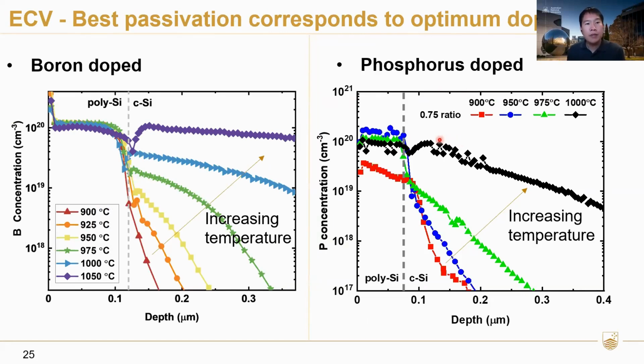Cool. So remembering that the optimum temperature is 950 degrees, these two images here show the ECV measurements of both boron doped and phosphorus doped. Essentially, if the doping is too low, the passivation is generally not as good, particularly for the phosphorus. So if the temperature is too low, the doping is not as high, and passivation is bad. But if the temperature is too high, then you start breaking down the interface oxide, and then you start introducing Auger recombination within the crystalline silicon wafer itself, and then the recombination starts to increase again. So the optimum temperature here is correlated with the optimum doping of the polysilicon. And this will be important later, where we can show that without any doping, you're basically not going to get any passivation with the polysilicon.